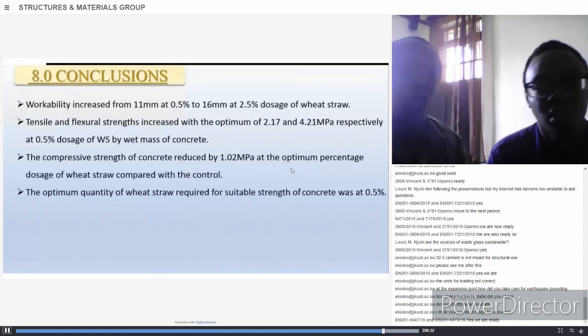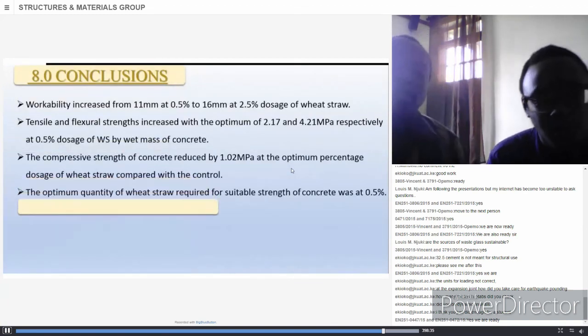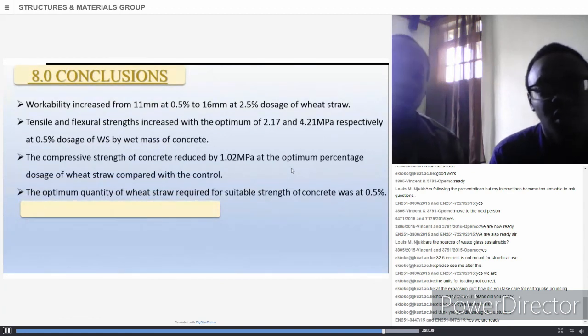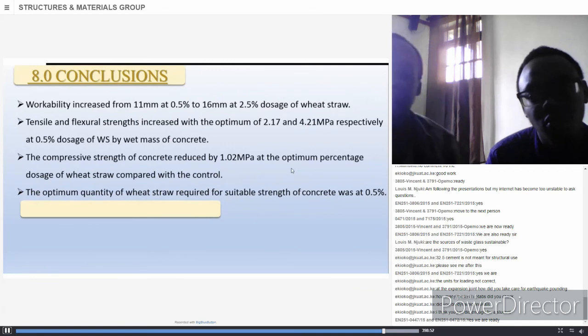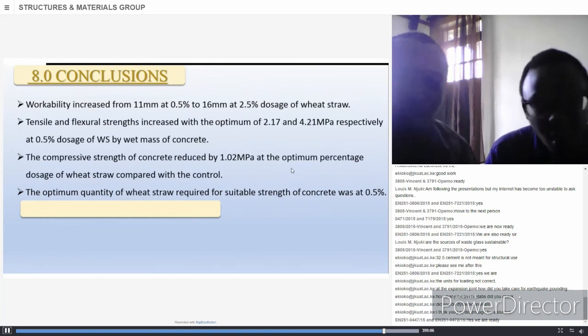In the conclusion, workability increased from 11 millimeters at 0.5 to 16 millimeters at 2.5 dosage. Tensile and flexural strength increased, with an optimum tensile strength of 2.17 MPa and flexural strength of 4.21 MPa at 0.5 dosage. The compressive strength of concrete reduced by 1.02 MPa at the optimum percentage. The optimum quantity of wheat straw required for suitable strength of concrete was established at 0.5%.